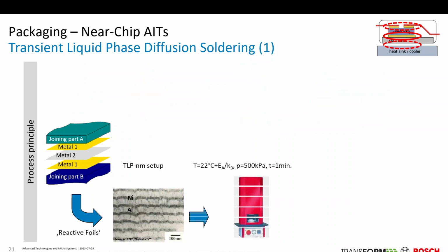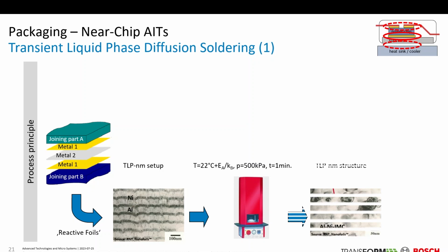Then you can use, in a quite similar way, so-called reactive foils. They work quite similarly, but the buildup is on the nanometer scale. Given here is the example with nickel and aluminum. You can apply a little bit of temperature, as you need activation energy. It could be temperature, it could be another source. As well, you need pressure and a little bit of time, and at the end of the day you get a diffusion soldered material, let me say the attaching system between joining partners A and B.